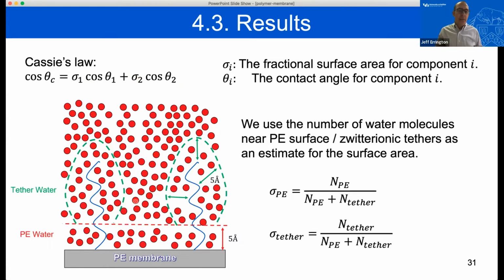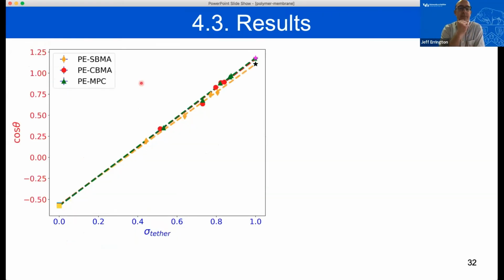And so in effect, what we were determining was the theta values associated with the tether and the theta value associated with the membrane. And then we put the data together to see the extent to which this Cassie's law could be used to capture how the contact angle evolves with this fractional area. And what we found was that this ends up being a very good predictor. So here are all of the data, and you can see that they collapse in a linear way as a function of the fraction of the surface that's associated with the tether. And so that linear dependence suggests that Cassie's law is a reasonable way, in this case, to estimate the contact angle associated with these composite systems.